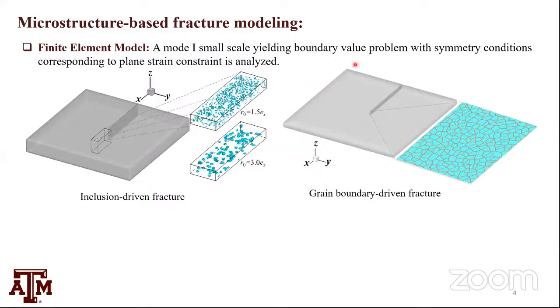So how do we do it? Finite element, well known. This has been there for a while. What we're going to do is take a specimen, a small scale, mode 1 small scale yielding boundary value problem. So I'm applying a loading condition that represents mode 1 small scale yielding. I've got a notch and a small region where I'm going to model the material microstructure. What I'm going to present is a simple microstructure. Either I have these inclusions, tiny particles that nucleate voids, or I have this nice distribution of grain boundaries. The crack in this case is driven by the grain boundary, so that's intergranular fracture. Or in this case, an inclusion-driven fracture. The matrix of the material is isotropic, elastic plastic.